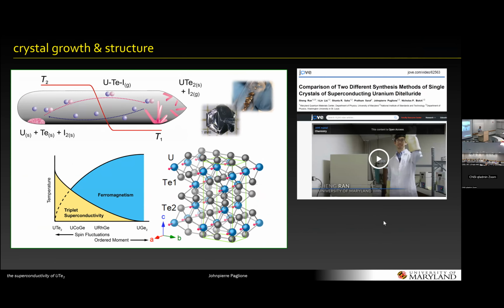I'm not going to go through a lot of details about the crystal growth and so on, but there are different ways to grow the crystals. And I'd say one of the nice things about this material is that there's reproducibility from different groups, several different groups around the world, growing the crystals, whether they're growing with vapor transport or flux growth or some other method. They get, for the most part, the same quality of crystals and same properties. So that has contributed to the fact that there's been so much work, about 100 papers in the last several years. And that's in contrast to some other materials where there's been a lot of materials problems to try to figure out and sort of tunnel through the noise and see what the intrinsic properties are.